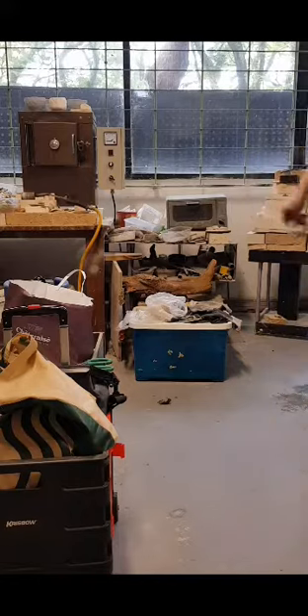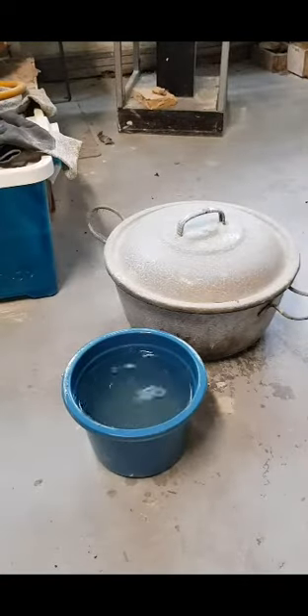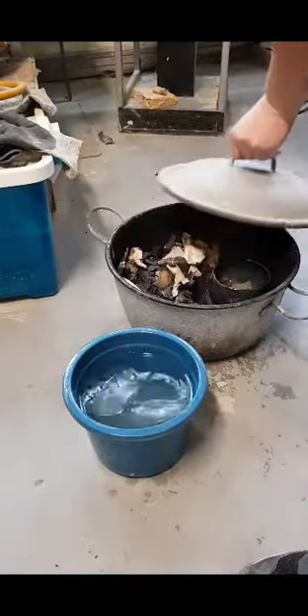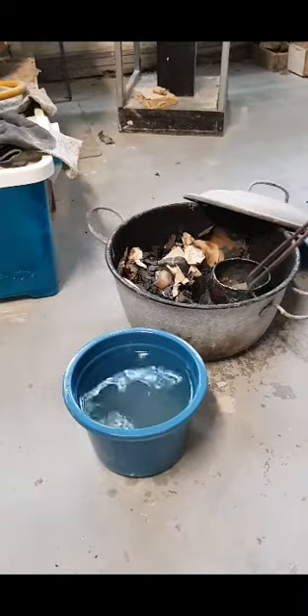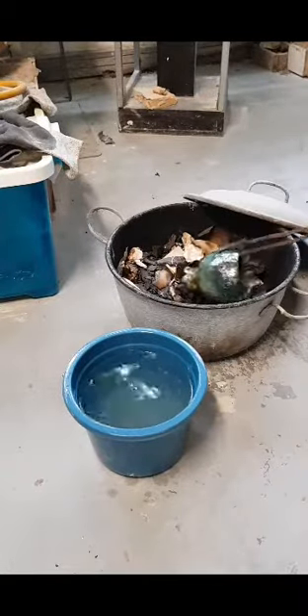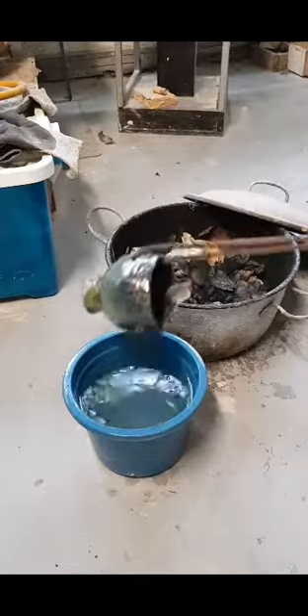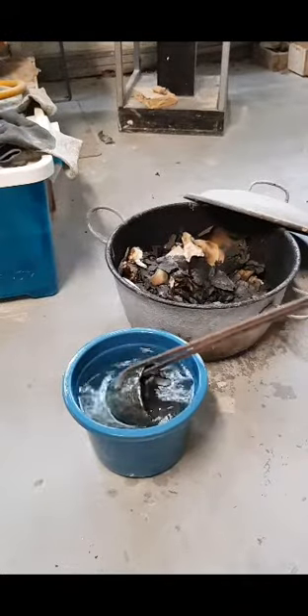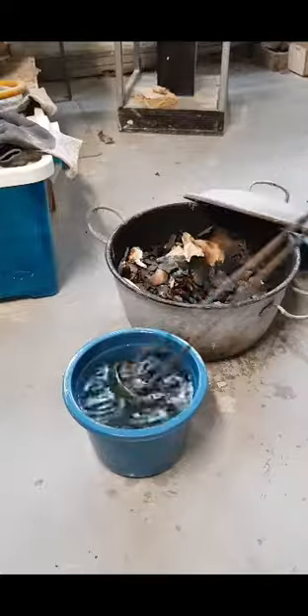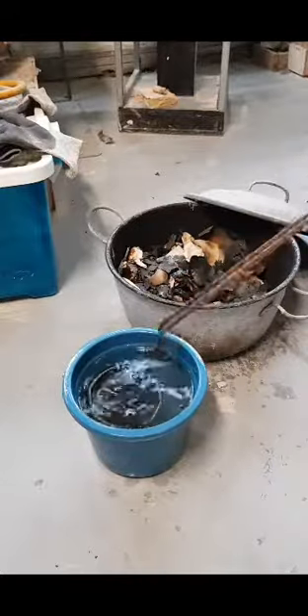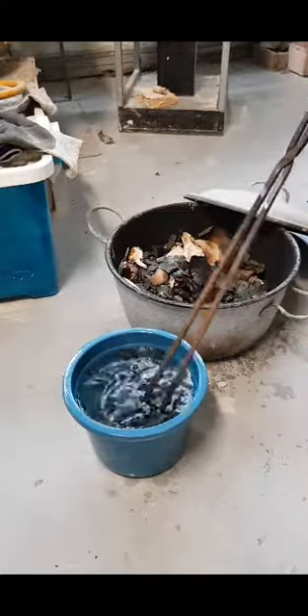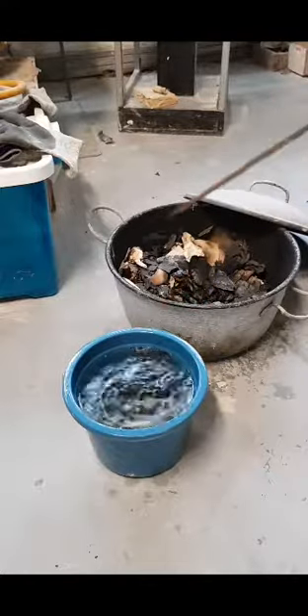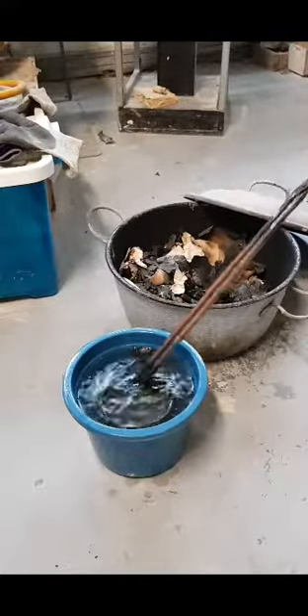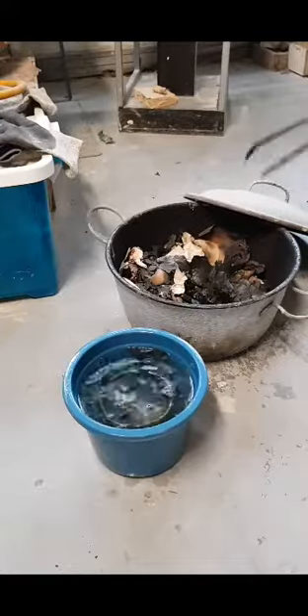If you skip the first process where you temper the clay and you do this, most of the time the clay will not be able to handle all that extreme temperature difference, and you'll end up with cracks. Since it has already been tempered with the sand, it is able to survive that extreme change of temperature. The pot has been in that can for about 15 to 20 minutes. That's usually enough to create all the effects that you want. So now I'm just quenching it in water to cool it down faster.